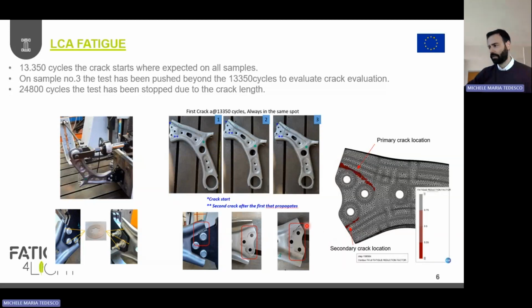This secondary one was recognized mainly in the third component, in which we went over the full test. So you can see here the crack, also in terms of length and shape, is completely similar to the one that we predicted virtually, and the second one is in this zone like that. So for this simulation, the correlation between physical and virtual was very accurate.